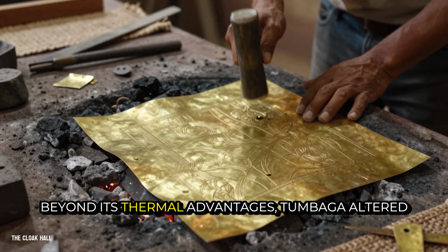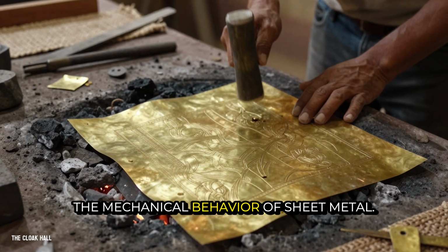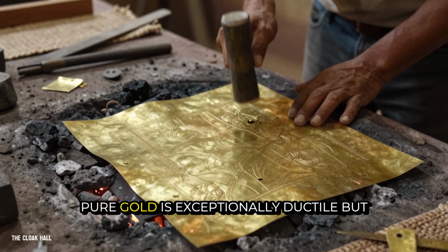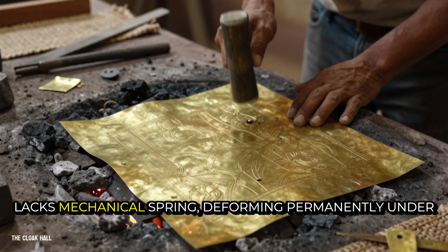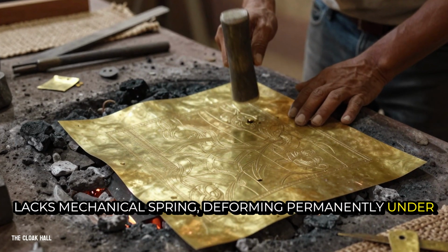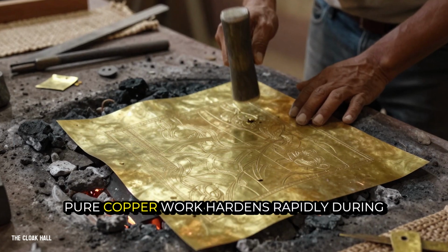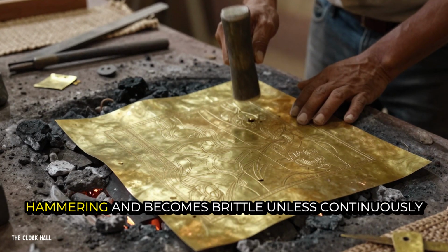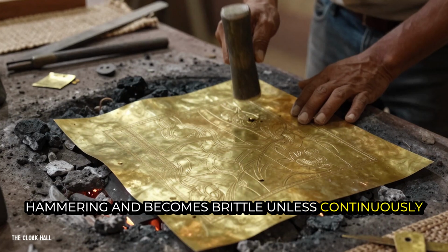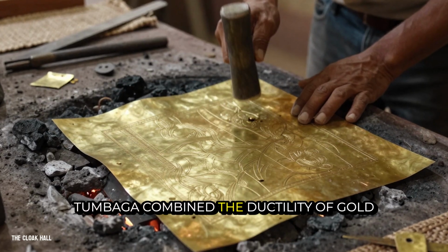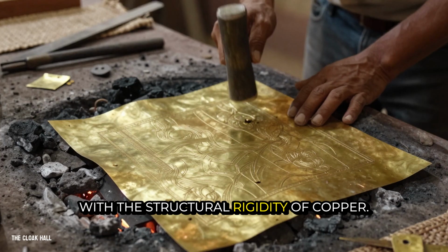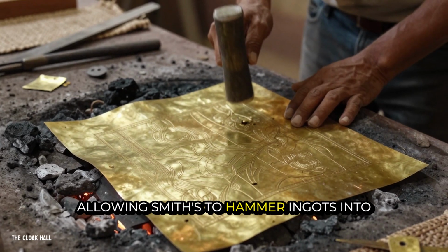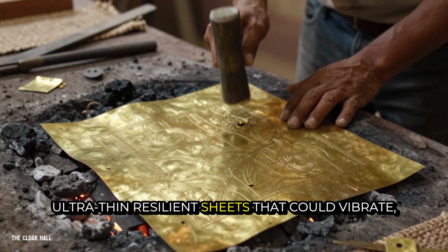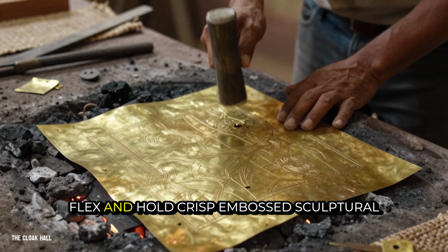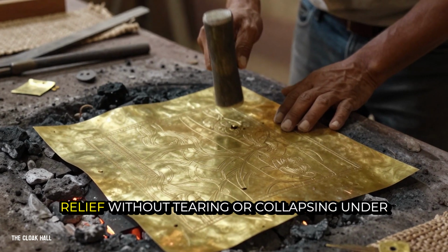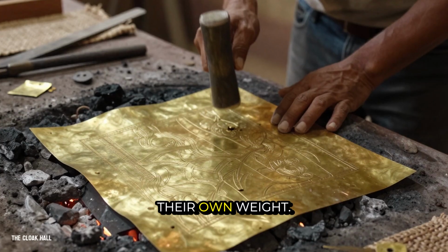Beyond its thermal advantages, tumbaga altered the mechanical behavior of sheet metal. Pure gold is exceptionally ductile but lacks mechanical spring, deforming permanently under minimal load. Pure copper work hardens rapidly during hammering and becomes brittle unless continuously annealed. Tumbaga combined the ductility of gold with the structural rigidity of copper, allowing smiths to hammer ingots into ultra-thin, resilient sheets that could vibrate, flex, and hold crisp, embossed sculptural relief without tearing or collapsing under their own weight.